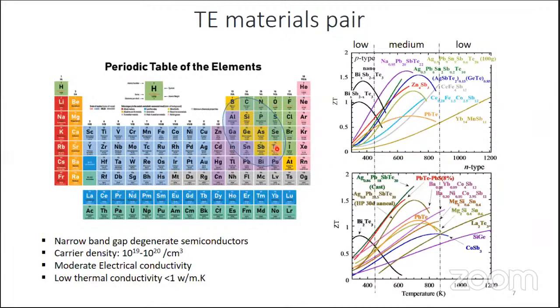Most impressive performance you can see in tellurium based ones, tellurium, selenium based ones, and now lead telluride and then antimony telluride. So one of the constituents is required mostly from here, and sometimes a transition metal in combination with the semi-metals is also tried. Normally the carrier density is between 10 power 19 to 10 power 20 per centimeter cube.